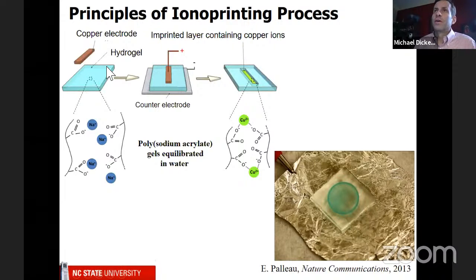This is the hydrogel. And the hydrogel is, again, mostly water. I don't remember the number, but it's like 90% water. It's remarkable how much water these things can hold. And it's held together by polymers. That's what I'm depicting here with these lines. And it's important to note that these polymers are ionic in nature. They have these sodium groups that allow us to do this technique. And so then we contact the gel with a copper, which again is like the penny, and we apply a voltage.